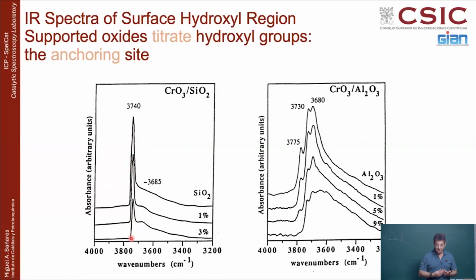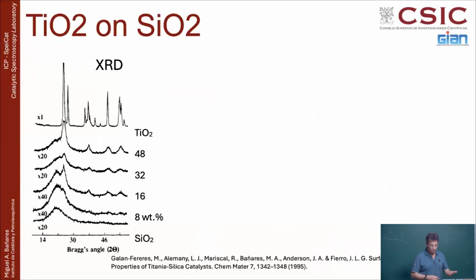In the case of alumina, the story will be similar, but doesn't look so elegant because you have many peaks. So the different peaks are being titrated. You will see that some sites will be titrated before others, and then you can make a story about where the chromium prefers to bind and so on. But in the end, the hydroxyl groups will be consumed. They will be taken. And so you can see that here they stopped at about 3 weight percent, and over here 9 weight percent, because alumina has much more hydroxyl, so it has much higher capacity to disperse and to have a molecularly dispersed chromium oxide.